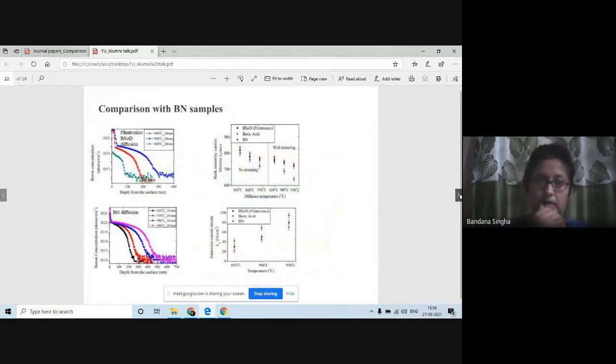And yeah, let us compare the results of all the dopant sources that we have used to carry out the experiment. As we see, the boron-rich layer thickness and properties vary depending on the dopant sources, and for the same diffusion condition, the boron nitride sample gives a higher junction depth compared to the spin-on dopant sources.